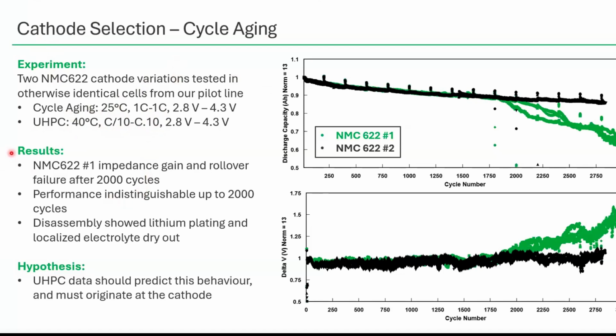We see that the results of the cycle aging, showing discharge capacity and this delta V, the difference between the average charge and discharge voltage, look very, very similar until about 1800 cycles. So this is pretty long into cycling. They had exactly the same delta V or voltage hysteresis. They had exactly the same discharge capacity fade. Everything looked really good for both until months and months into cycling.